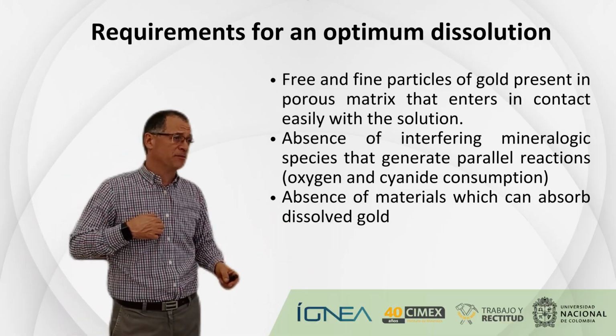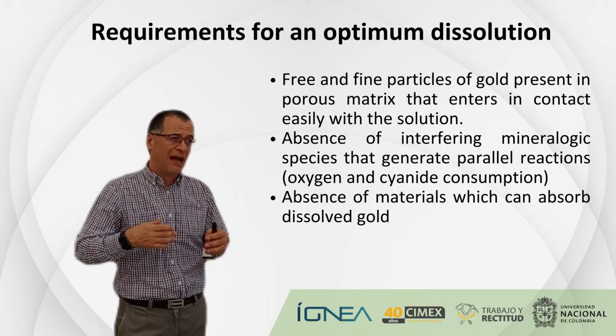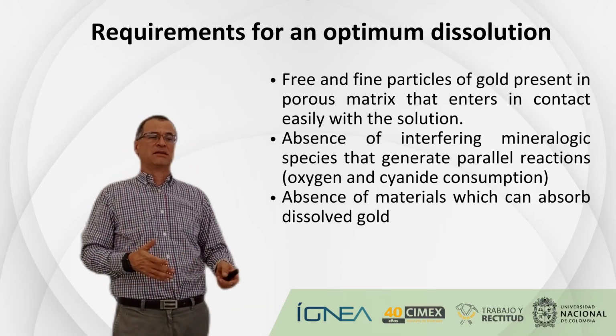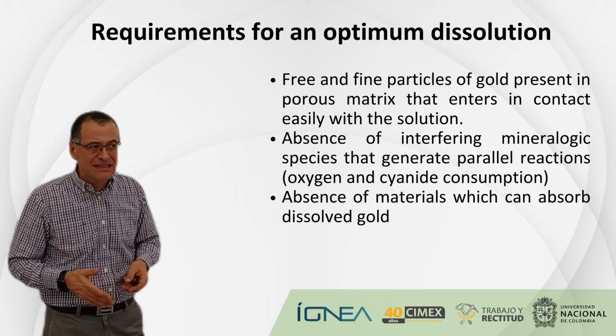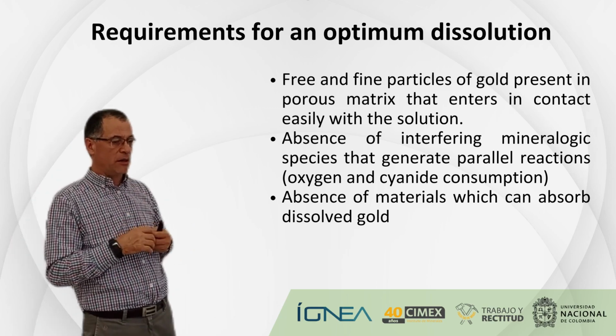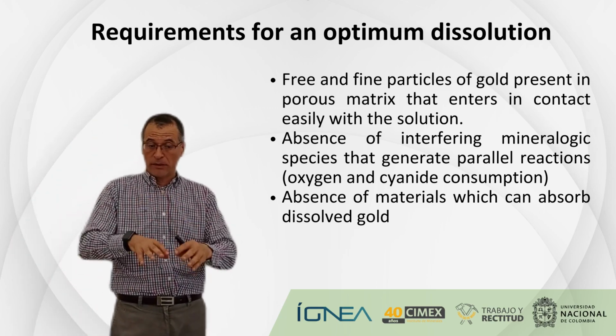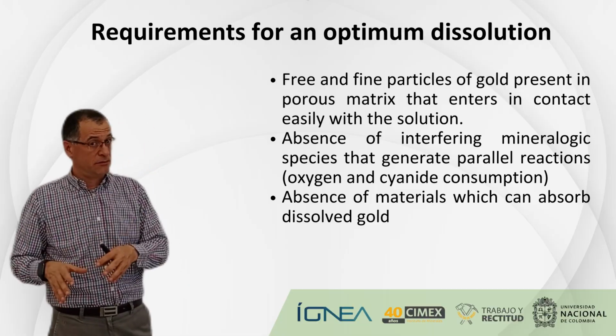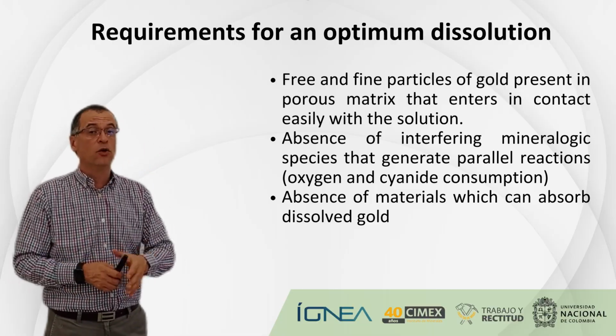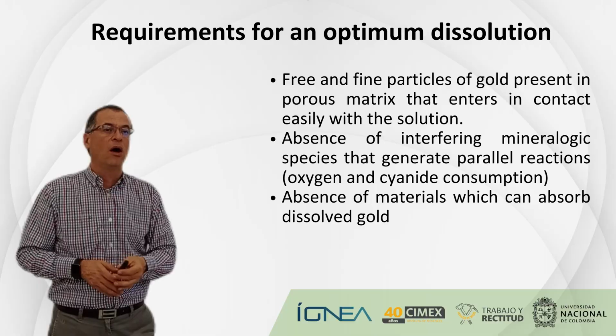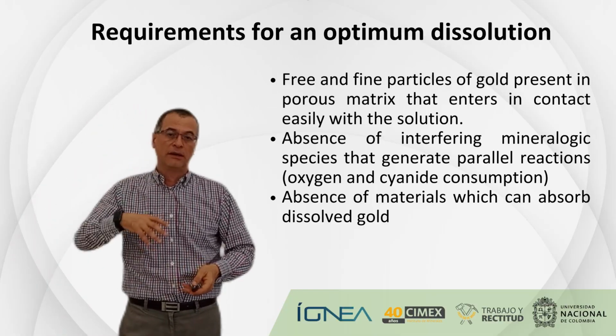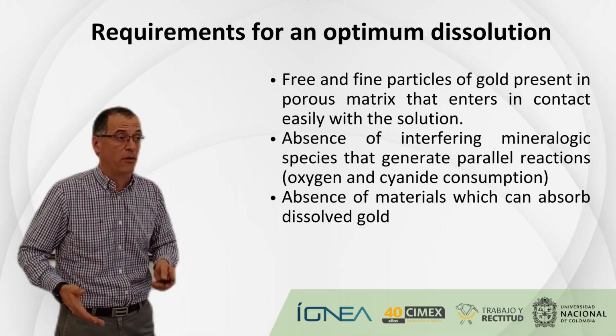And don't have the presence of materials that could absorb the gold. When the gold is dissolved, some materials, such as carbonaceous materials, could precipitate and reabsorb the gold, and this is a real problem in the process.